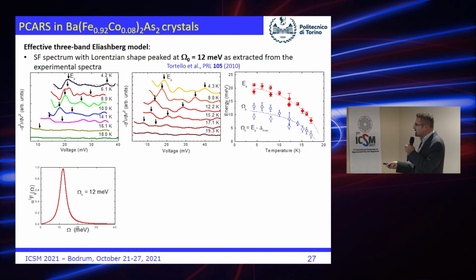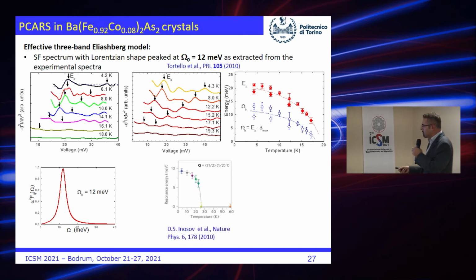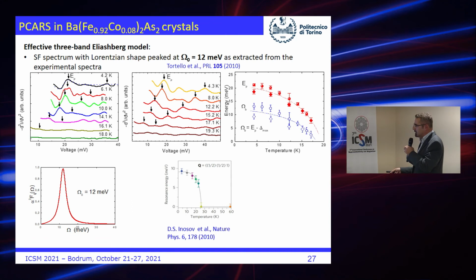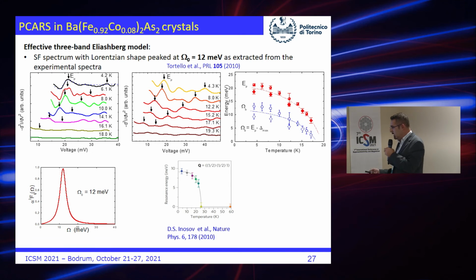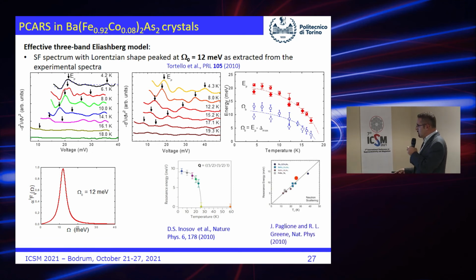and you see that this is the temperature dependence of the bosonic frequency. That is, of course, not identical, but at least in agreement qualitatively with what is expected from inelastic neutron scattering. Then, here I have something which is around 12, more or less. Let us choose a function that is peaked at 12. And we compare this with the scaling law, and it is not so far from what was reported.